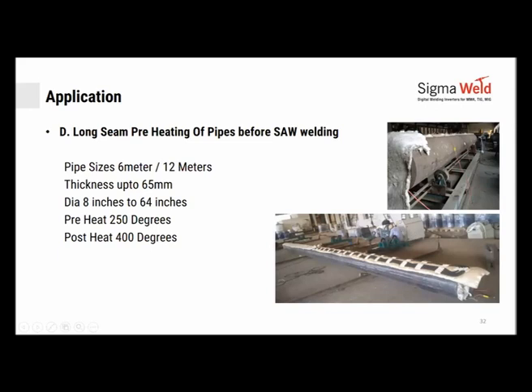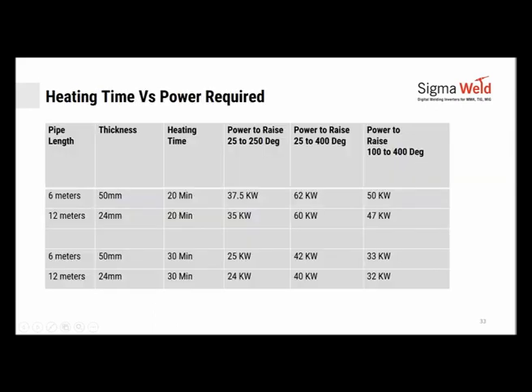Before induction, we had a huge gas bank here, which used to be maintained to continuously keep the pipe heated to about 400 degrees post welding, and pre-welding at about 200 to 250 degrees. This is a classic case where we checked that their welding time per length was about 20 to 25 minutes. So we calculated the power in a way that one pipe could be preheated while the other is being welded, so that your more expensive equipment, that is your column boom and the welding that is happening, doesn't stay idle.